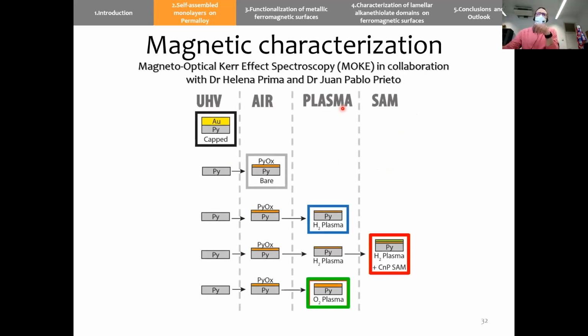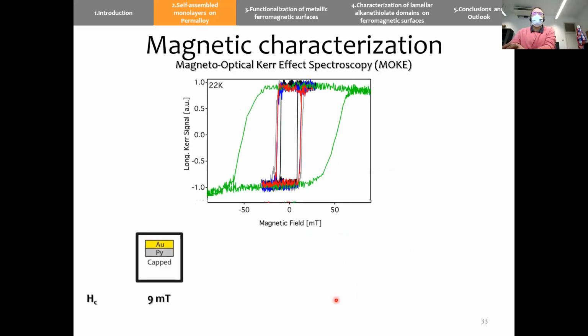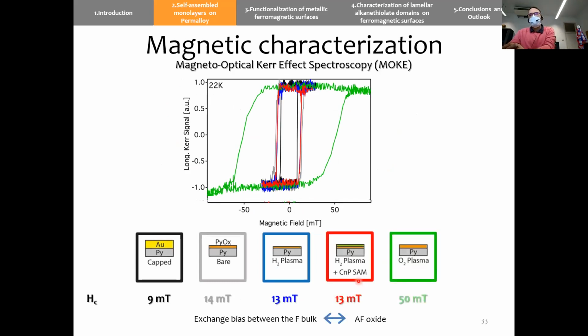We prepared different kinds of samples: a standard, an oxidized, hydrogen treated, hydrogen plus SAM, and oxygen. And we can observe that there is a clear difference. We don't observe any difference between the hydrogen plasma treated and the hydrogen plus SAM. And when we increase the quantity of oxide, we observe an increase in the coercive field, which is due to the exchange bias between the bulk and the oxide.